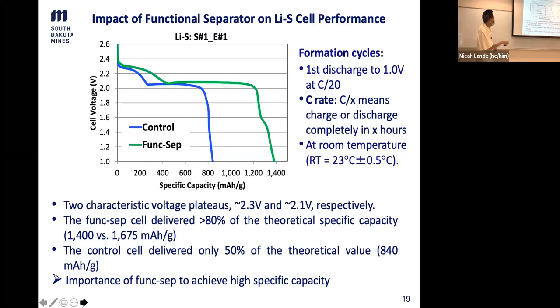So for this advanced cell, it delivered more than 80% of the theoretical specific capacity, which is actually considered very good, given the sulfur chemistry. And if you look at the control cell, without this functional separator, those plateaus are shorter, which leads to the smaller specific capacity, only like 50%.